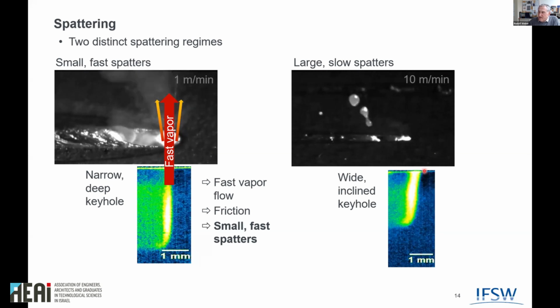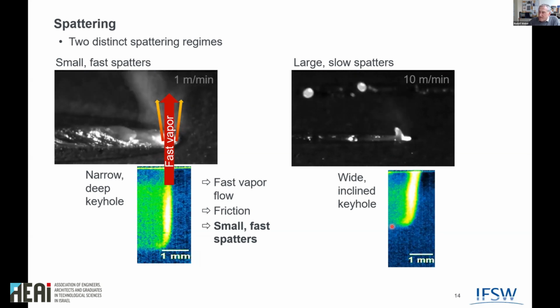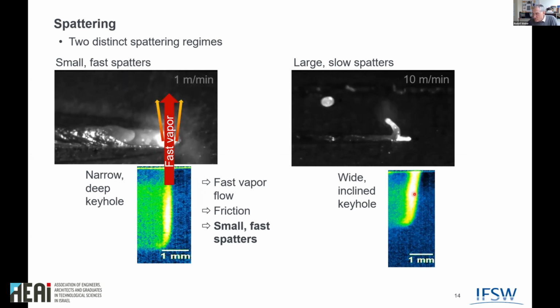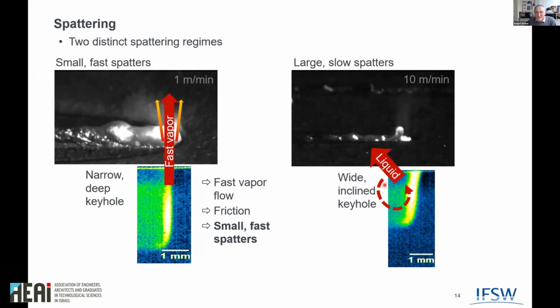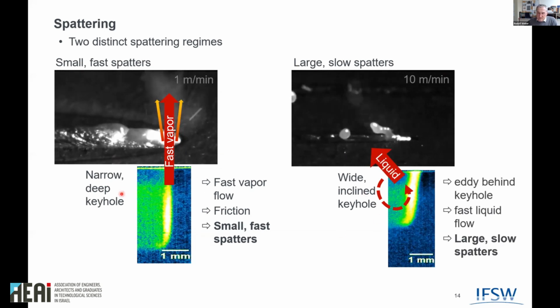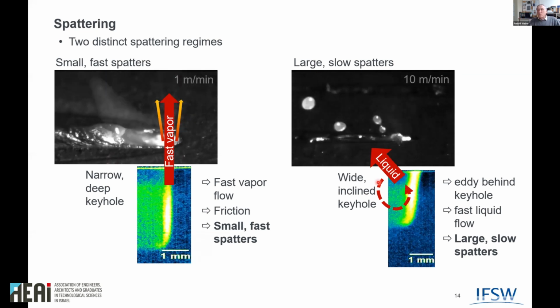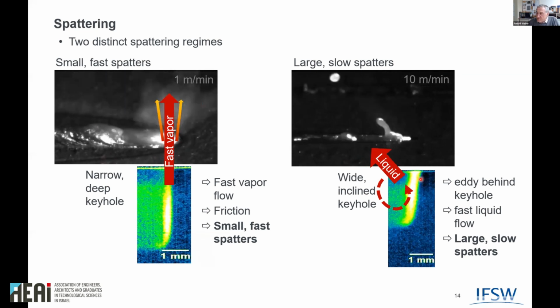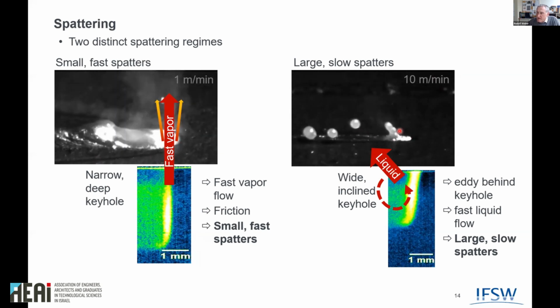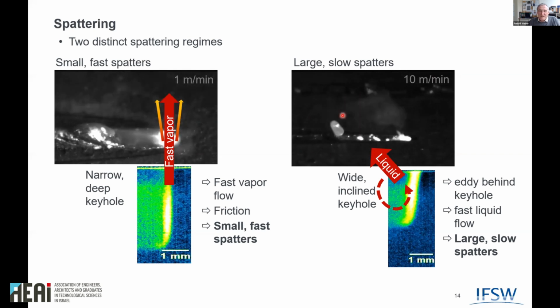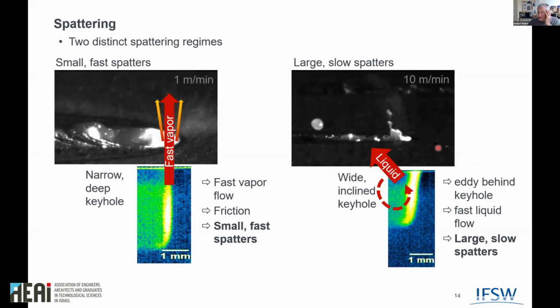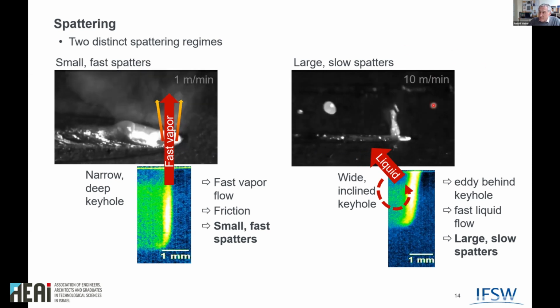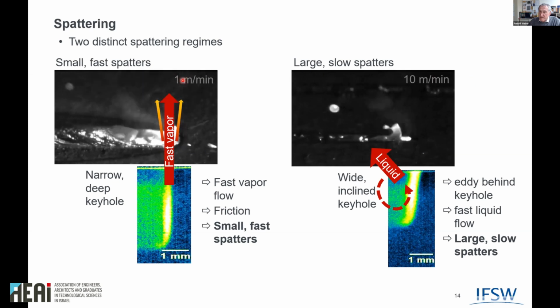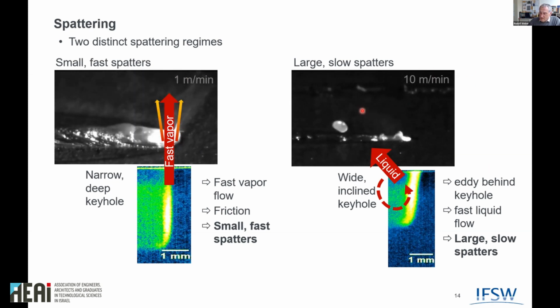This is completely different. Now the capillary is wide and inclined a little bit to the back. And what I cannot show, but you have to believe me, there is a strong eddy behind the capillary, which is not the case here. A very strong eddy which moves the whole liquid up, and if the surface tension is not enough to hold back the liquid, you see that we have really large droplets which just blow out of the complete system. So with the large and inclined capillary at higher speeds, you have to compare the welding speeds also, we can create these large bubbles.